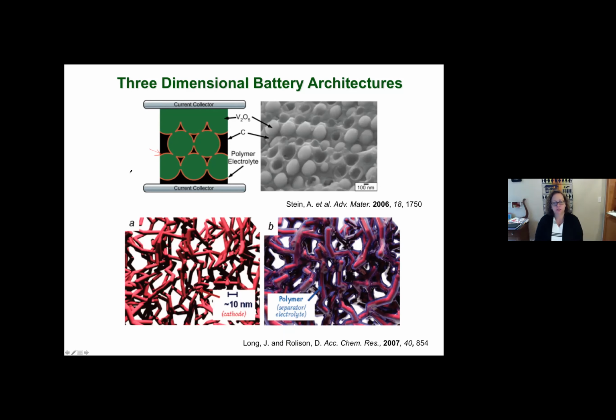So the challenge that his group had at the time was that the polymer layers were very thin, so there were some pinhole defects. And so what that leads to is basically a non-charging behavior or a very leaky capacitor-like device. The example on the bottom is from Deborah Rolison's group at the Naval Research Lab. This would have been the highest power density 3D battery by far because the surface area is so high.